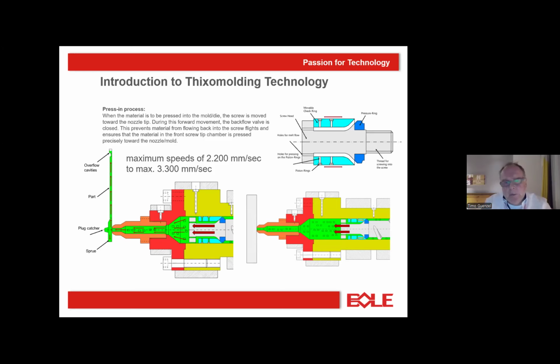Thixotropy means when you have a semi-solid material and apply friction to that material, then you can reach a longer flowway. That is the principle of thixotropy. That means on a Thixomolding machine, you can have longer flowways with lower wall thickness, and you do not need so much speed. Our experience is you can have a ratio of flowway to wall thickness around 400 to 1. That means when you have a wall thickness of 2 millimeter, you can have a flowway from the injection point to the end of the part of 800 millimeter.